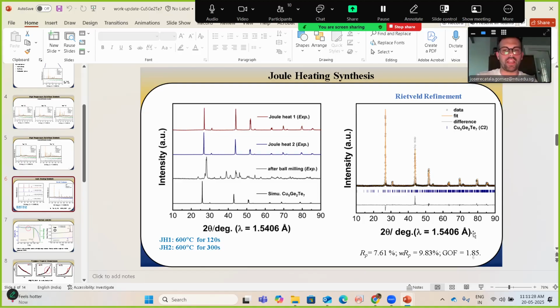So I would say, Jayant, do some EDS. See if you have germanium telluride. If you don't, then that's a different possibility and we can look into it differently, right? So let's go to the most likely probability, which is that you have some germanium telluride that has precipitated. Hopefully not. But that 2 theta, that 27, is where germanium telluride appears. So hopefully you don't. And your refinement is pretty good, man. Your values are fine. Your peaks are well fitted. Seems fine to me.